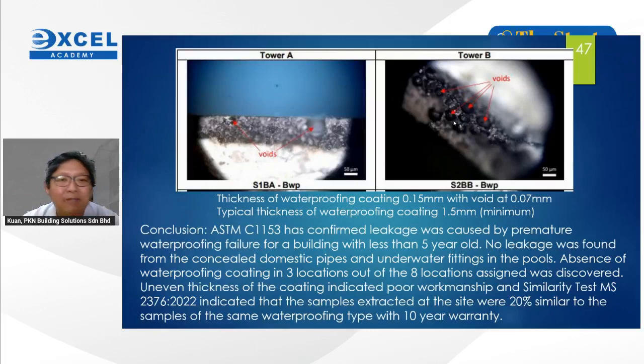I have a reasonable ground to suspect the waterproof has been diluted, because without dilution, this type of bituminous compound cannot have bubbles, you see, and the voids were the bubbles. So, being a licensed applicator, I can testify on the workmanship, and my polymer scientist can testify on the material failure. So, the conclusion is, poor material.